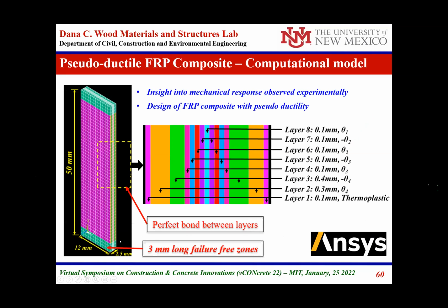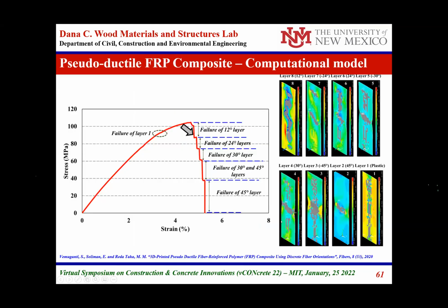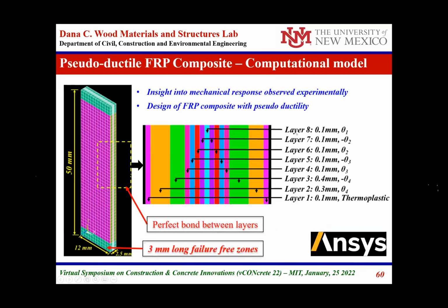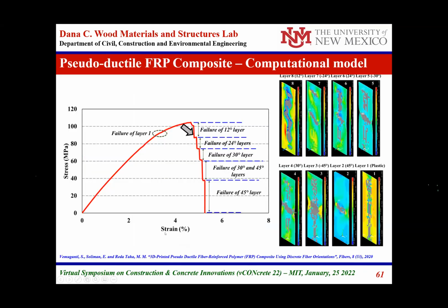And then we went to the finite element and designed a behavior that would show some pseudo-ductility. You can see this pseudo-ductility here - this is a different layer number, but this is the thickness of the different layers at the different angles. And through our modeling, we showed that we can have some sort of progressive failure where the failure wouldn't happen suddenly and would have some ductility in it.